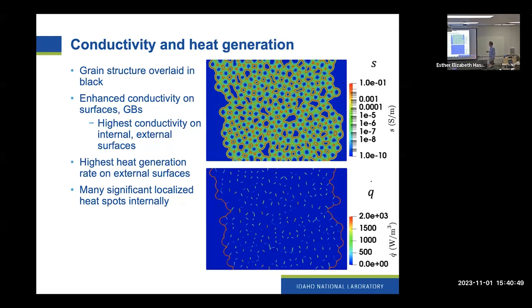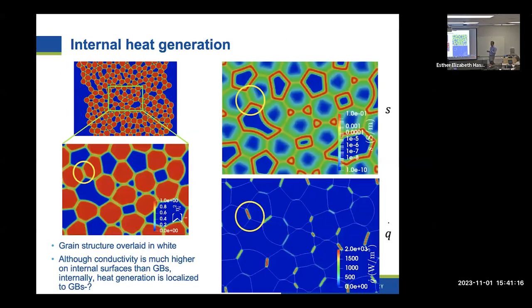So if you look at the resulting heat generation from Joule heating, you see that due to the high concentration of defects and the high diffusivity of those defects on the surfaces, there's quite a high heat generation rate at the surfaces, but there's also quite a high generation of heat within the grain structure itself. So we wanted to try to understand that better. So we looked a little bit at this zoomed in region at the center here.